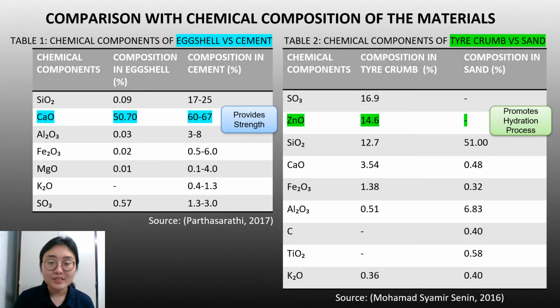For your information, Table 1 contains the chemical components of the eggshell versus cement. Table 2 contains the chemical components of the tyre crumb versus sand. The calcium oxide in the eggshell was found to be similar in amount to the calcium oxide found in the cement, which provides the strength to the cement. The zinc oxide found in the tyre crumb promotes the hydration process of the cement.